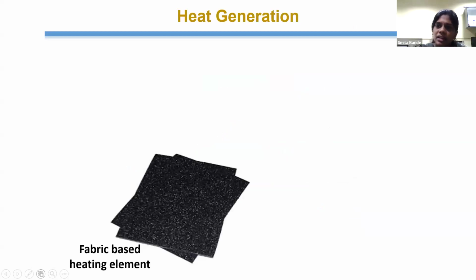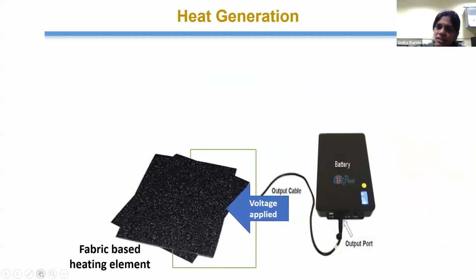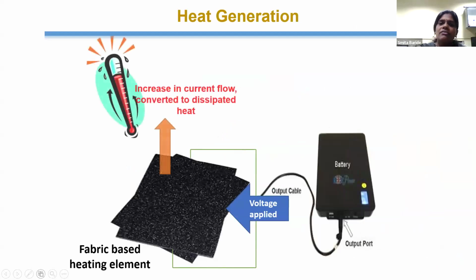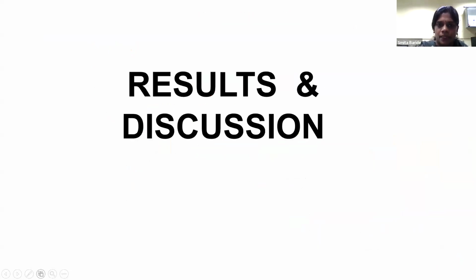Basically, what happens is, being conductive fabric, it has a low resistance. And when we apply some voltage to it, it will increase the current flow and it gets converted to dissipated heat. And if we insulate it properly, that heat can be retained for a long time. So this principle is basically used for high altitude clothing and for electrically heated pads or jackets.